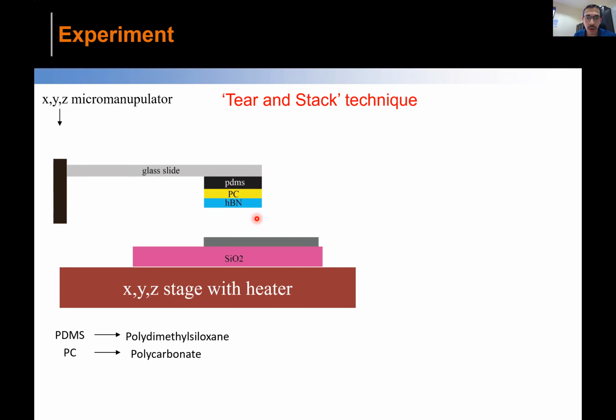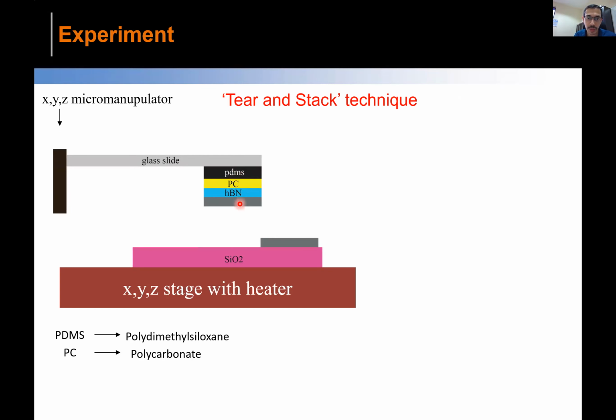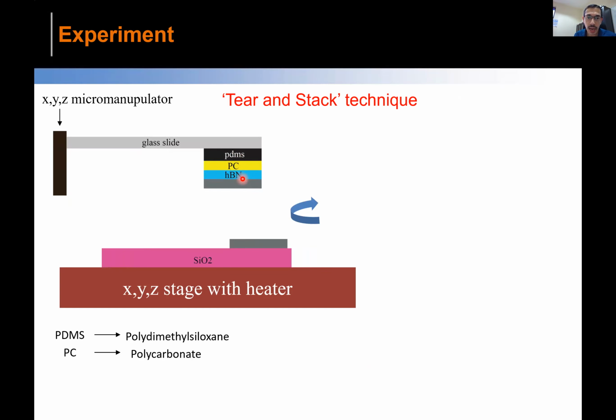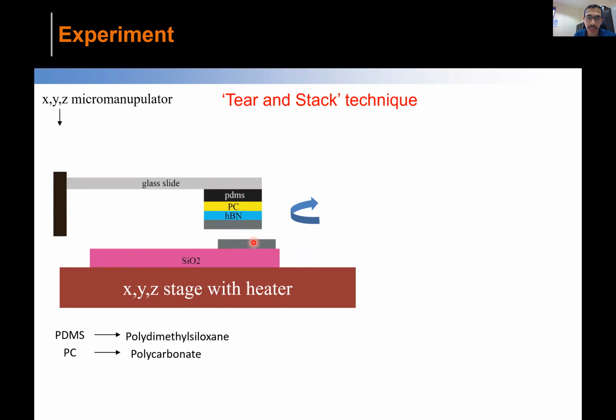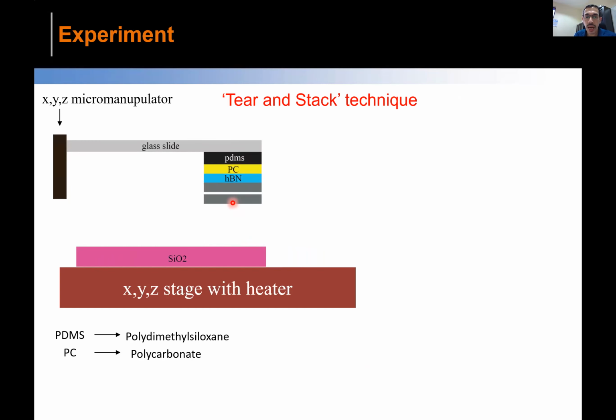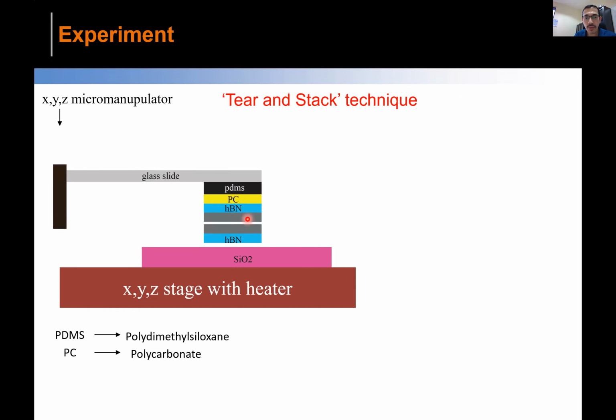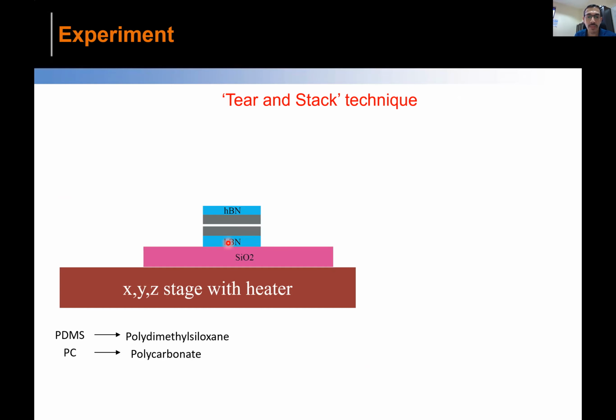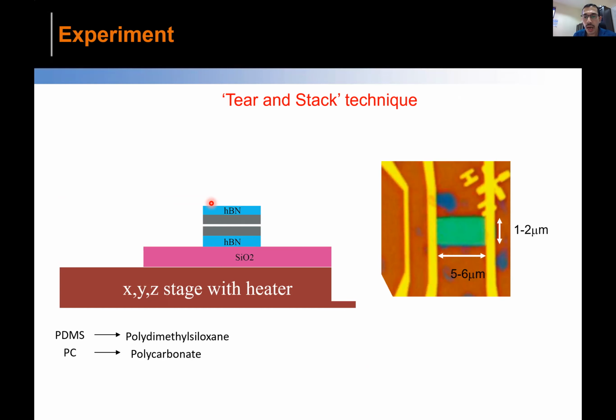So we have some kind of stamp here, as you see, PDMS PC, and we take a single layer graphene and we cut it into two pieces, and then we make a relative angle between them, and these are encapsulated by boron nitride. If somebody is interested, I can discuss it at the end of the talk, but I'll not go into details. There are lots of techniques we have achieved over time and so on.